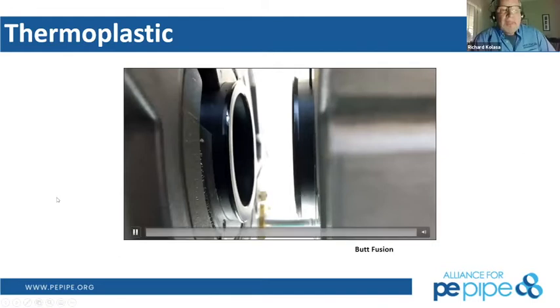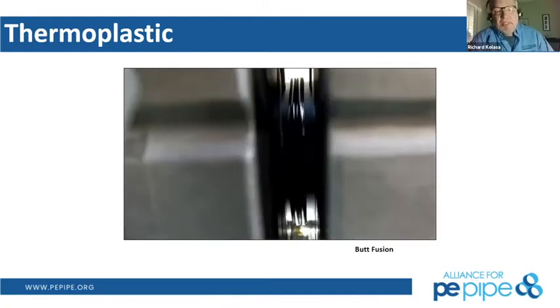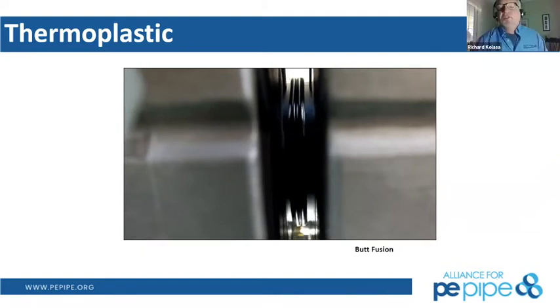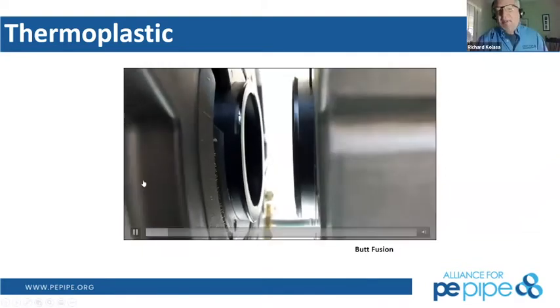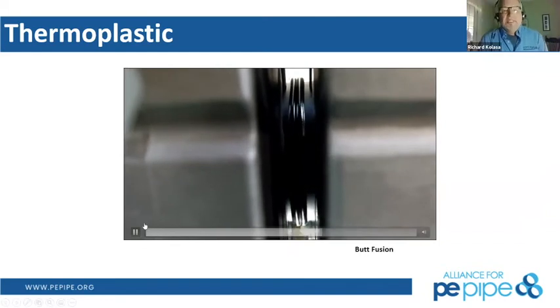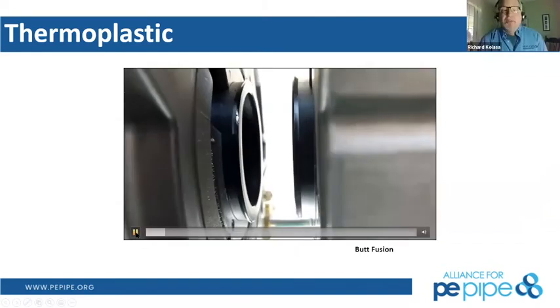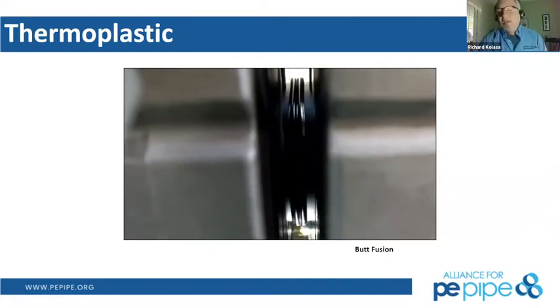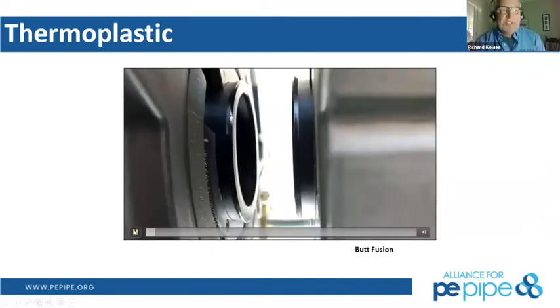Here's a little video of the fusion process after the heater plate has been removed. The surfaces are nice and smooth and clean, and then the rollback bead forms on that polymer. Just like that initial picture that we showed you, that's what's happening. When those forces come together, they force that material to the inside and outside of the polymer, but the design of the pressures used and the cooling times, etc., are all based on maintaining that interface where those polymers will actually chemically bond together. That's the fusion process, and that's the jointless, monolithic system that we create once completely cooled under the regulated procedures.